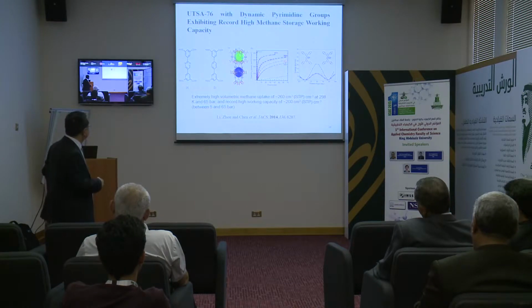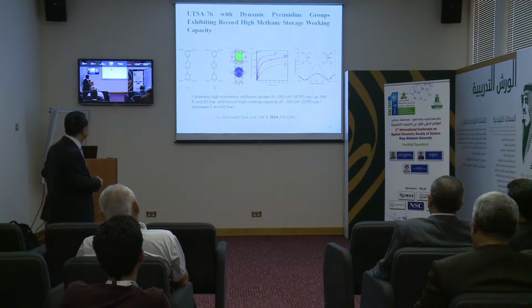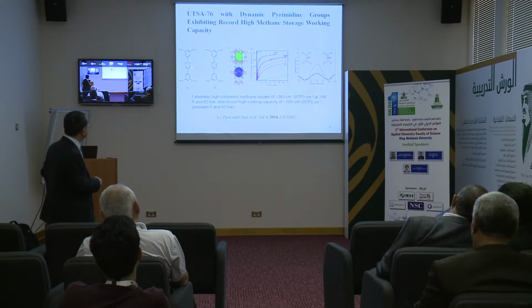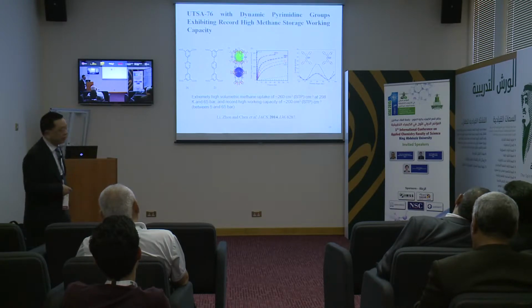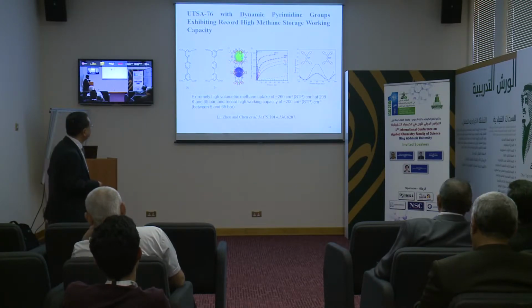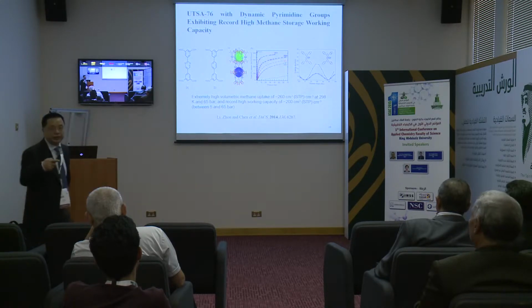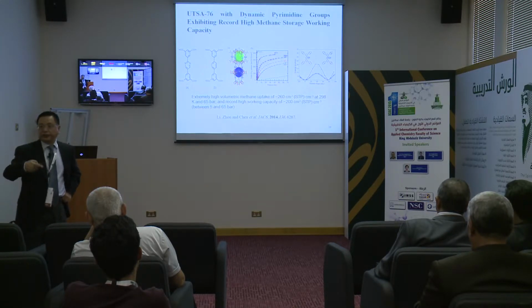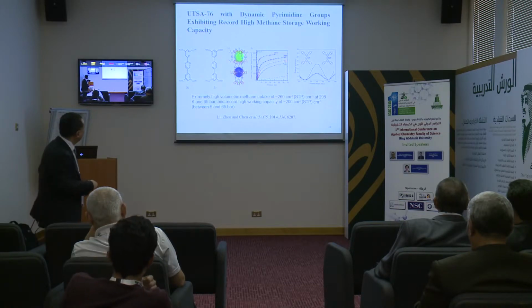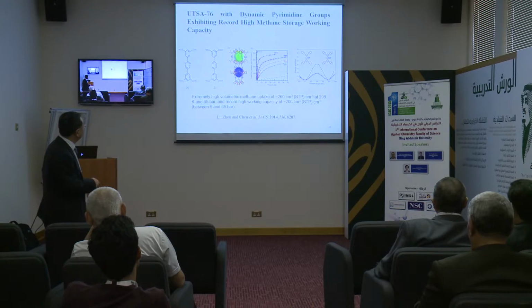So this is quite an older one. We quite accidentally realized that immobilizing these pyrimidine-type sites can enhance the storage capacity. At this moment, the mechanism is still not so sure. But the one thing I want to mention is that this significantly increases the storage capacity, by about 30 cc. This is quite significant.